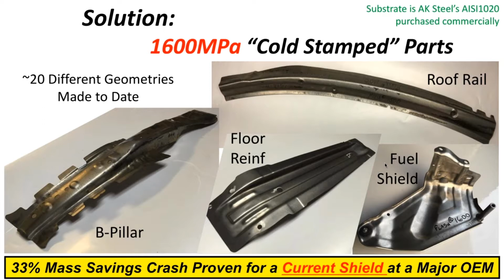On the lower right inset is a fuel shield. We were actually able to reduce the mass of the current production part from 3 pounds down to 1.3 pounds. That's a 57% mass reduction and still pass baseline testing after 7 days of work at an OEM test lab testing dozens of different parts. They had actually talked to us, once we get in production, about doing just a 33% mass savings for this current shield at the major OEM.